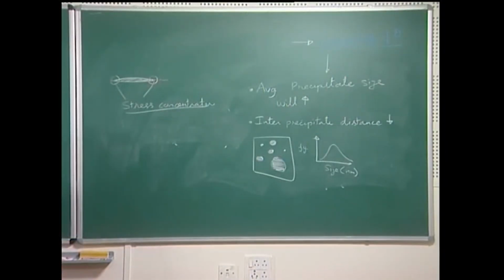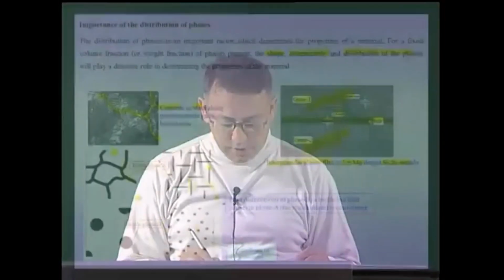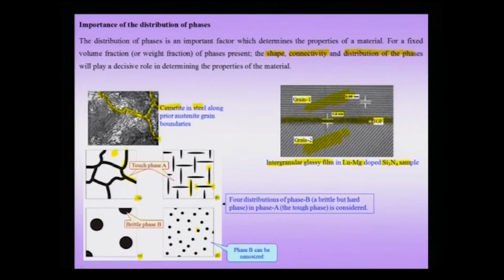On the other hand, suppose I consider the same distribution of B in A like in the case of C or in the case of D. Then you notice that the same phase is present in the form of a sphere, of course depicted as a circle in 2 dimensions, and in that case the stress concentration effect is much reduced. Therefore, the propensity for crack nucleation at the second phase particle would be reduced.